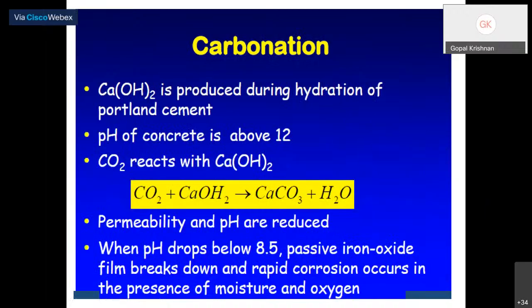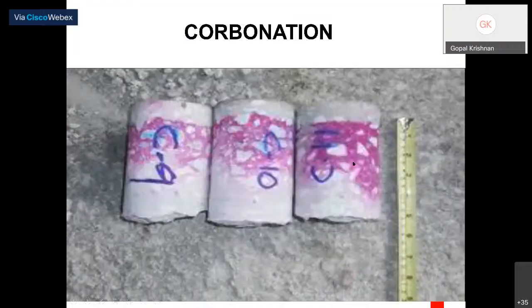The next one is carbonation. Carbonation process and carbonation chemistry, you all know, so I'm not going to repeat it. The pH should be above 12, and carbonation drops the pH below 9 or 8.5, so that the passive layer breaks down and corrosion progresses in the presence of oxygen and moisture. When you take the core, you can spray 0.2% concentration phenolphthalein, and we can see where the color changes, so that we can measure the depth of carbonation from the surface.